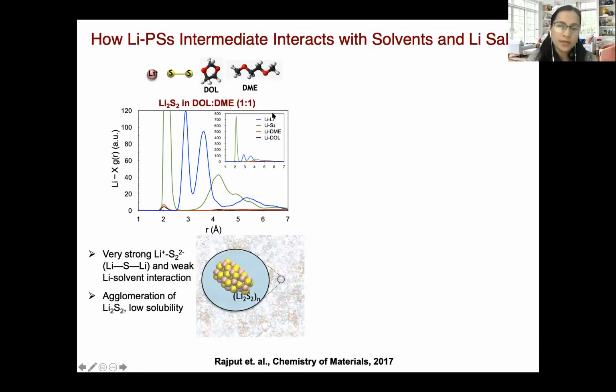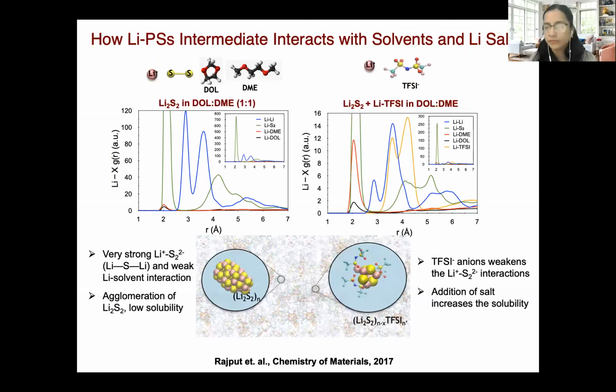And then when we looked at the solvation structure of lithium-lithium, we observed this very well-defined long-range structure, which is an indication of these polymeric species forming in the solution, where sulfur basically acts as a bridge between different lithium ions, and we form these lithium-sulfur-lithium ionic chains. And due to that, the solubility of Li2S2 in the solution is very low. But likely when you add salt, lithium TFSI salt, to the system, things are going to change. And that's exactly what happened.